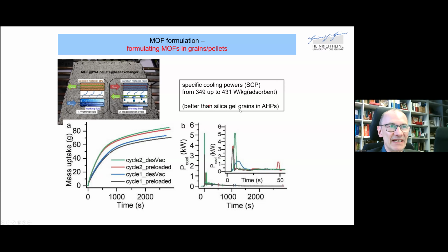So that is a little bit better than silica gel grains, which could be prepared similarly and brought also into this heat exchanger. You also see what I told you before, that this uptake until the MOF is fully filled doesn't take much time. So here it's about, let's say, 500 seconds until we reach about 60% of filling. And one would not run this process to full equilibrium or to full uptake. That's not economical. So after, let's say, 500 seconds, one could turn this process around already.